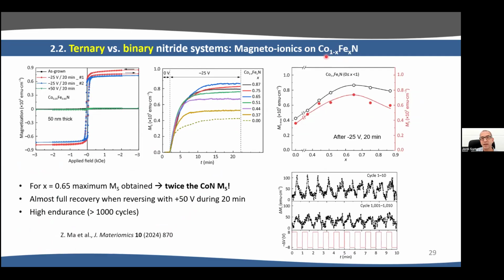So we next studied the ternary cobalt iron nitride compound, and we saw that when we induce magneto-ionics, the best composition, so here as a function of iron content, this discontinuous line is cobalt nitride, and then when we add iron, the magnetization improves. So you can see it more than doubles, multiplies by a factor of 2, basically, the achieved magnetization. And the best composition is for 65% of iron. And here in the loop, you can see that we can generate this high magnetization. So if we calculate the saturation magnetization from this loop or from the moment versus time, we get these curves where basically you can see the maximum is at 65% of iron in this compound. And the cyclability for this material is very good even after 10 to the 3 cycles, even after 1,000 cycles.